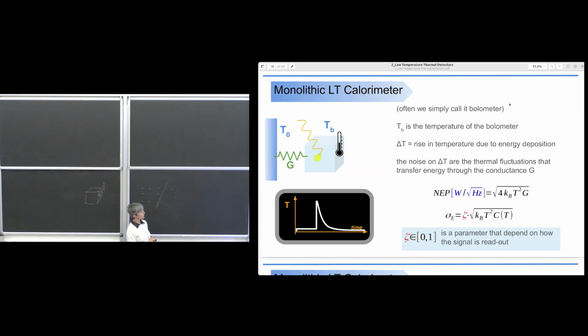You have the temperature of the bolometer, that in principle can be different from the temperature of the thermal bath, but we will go back to that in a while. You have an increase in temperature that is proportional to the energy released and to the heat capacity. And you may wonder what is the intrinsic energy resolution of this device. The intrinsic energy resolution depends on the fluctuation of the phonons or heat you produce that increase your temperature.